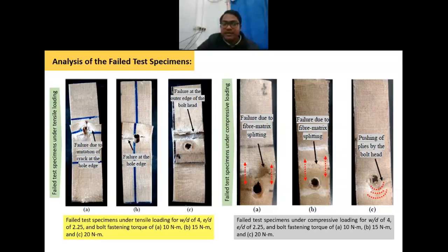Under tensile loading, you can see there are different modes of failure, like failure due to the initiation of a crack at the hole edge, and failure at the outer edge of the bolt head. This type of failure is observed when the bolt fastening torque is maximum, that is 20 newton meter. So failure occurred at the outer edge of the hole, not in the hole. At low bolt fastening torque, the failure occurs in the hole, but at higher fastening torque, the failure occurs at the outer edge of the hole. That's why it's giving me the best result in terms of maximum failure load.